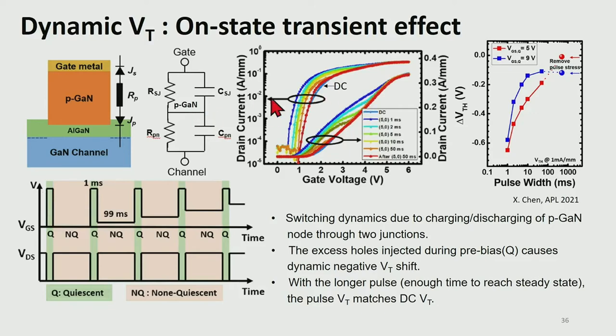So if you see this center figure, compared to the transfer curve measured with the DC setup, the pulse transfer curve after the positive gate voltage stress shows more negative VT. But if you use a longer pulse or wait for enough time, the excessive holes in the P-GaN can be consumed and the gap between the pulse measurement and the DC measurement is reduced. So because of this dynamic effect, the amount of the VT shift can also be dependent on the measurement setup in this P-GaN gate structure.